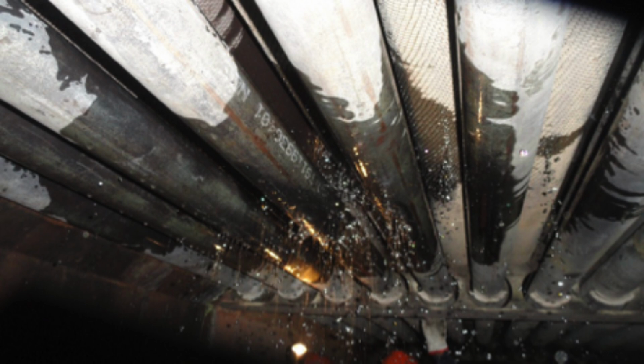So this is the bottom side of tubes of the heat exchanger, and unfortunately the picture is not that clear, I think, but there's water running all the way down here. And these actually failed every 6 months from the install. It was a new plant that they installed, and every 6 months they had failure. And when they analyzed the corrosion products, they also found chlorides, and therefore they said it was the chlorides and the water treatment. And there were quite a few stories given for the reason for these failures.